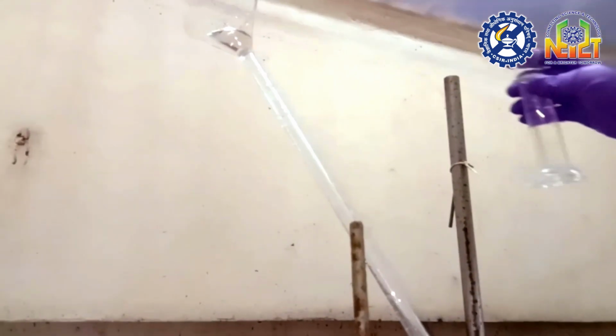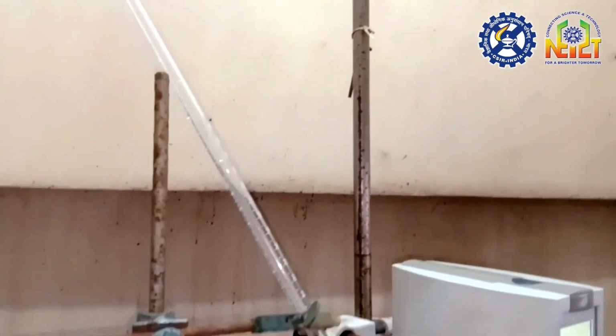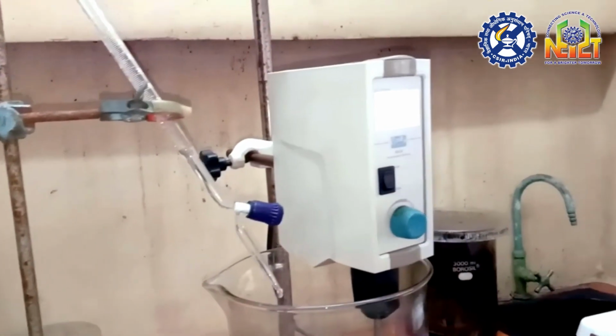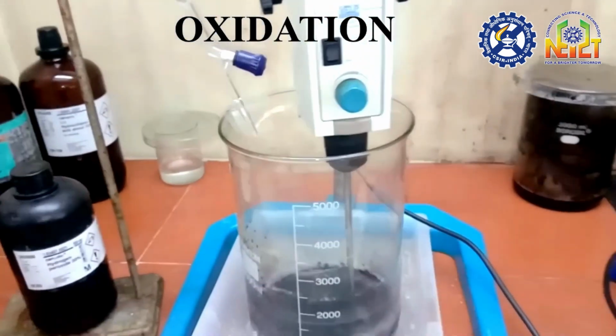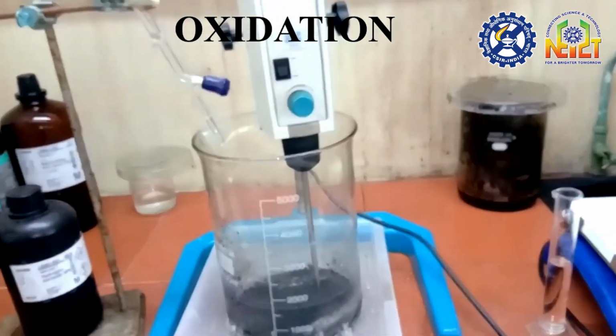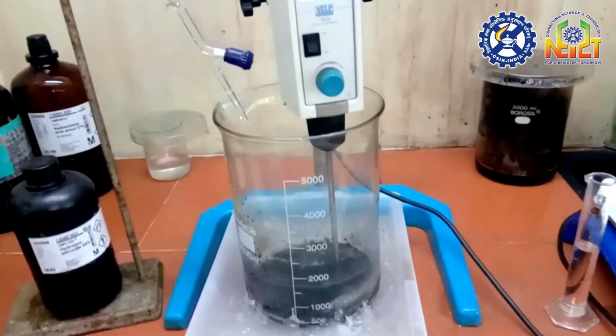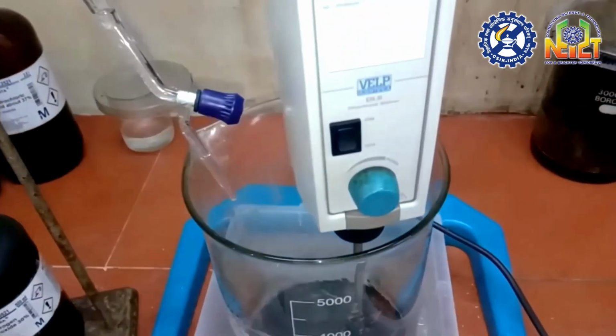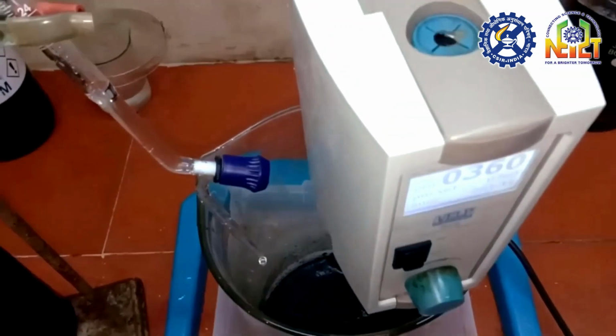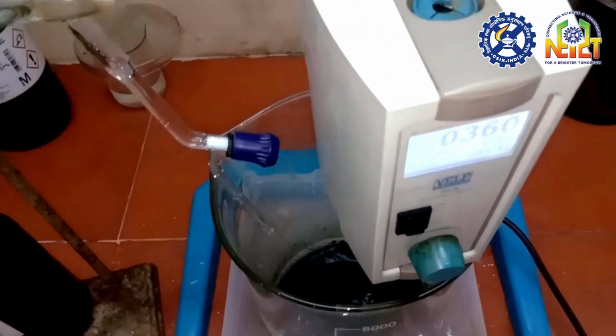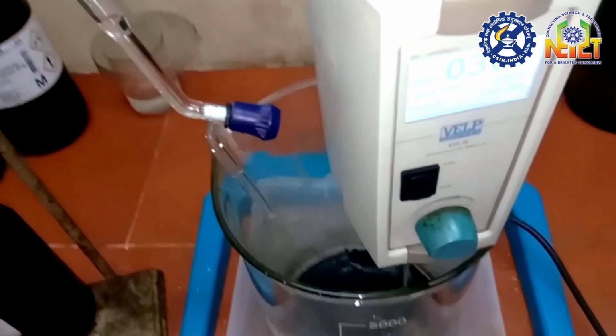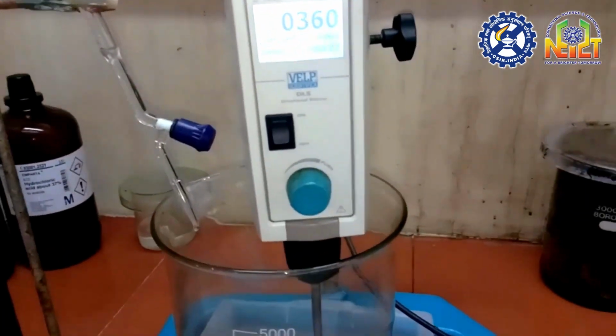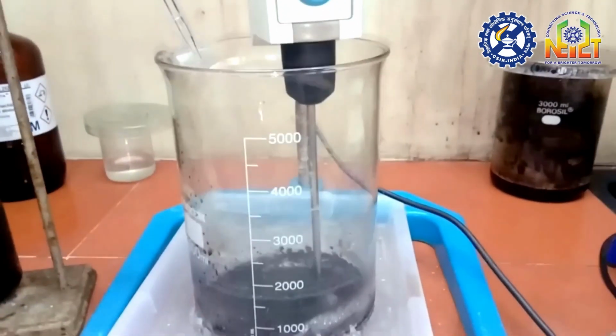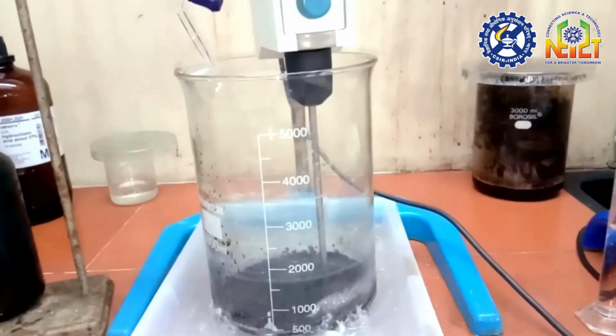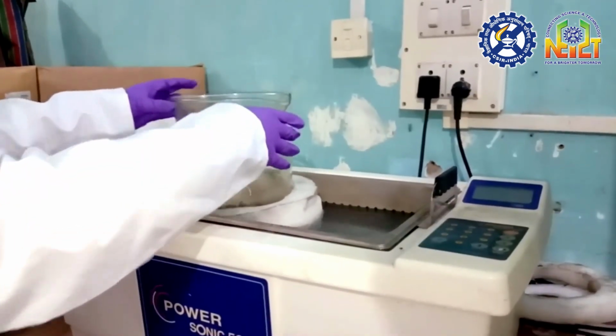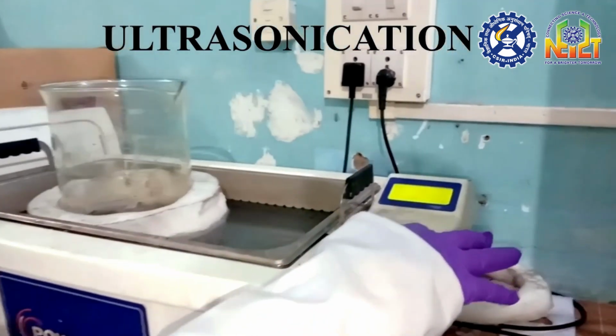After coal washing, for the oxidation of the coal, the oxidizing agent was added drop-wise from the burette while stirring the coal slurry in ice-cold condition to control the exothermic reaction. The reaction mixture in the beaker was ultrasonicated for 6 hours after the oxidizing agent addition.